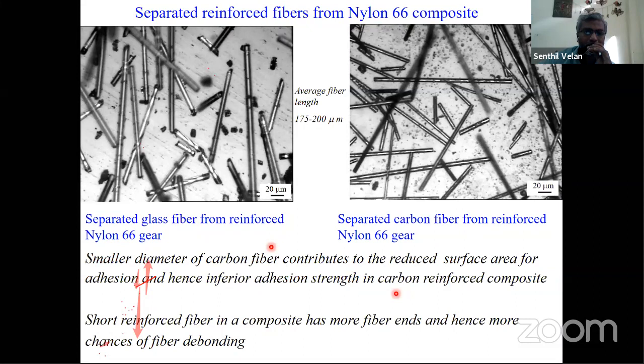What is more important is the size. The smaller diameter means, again, these are in microns. If you look into this, the average length is in the 175 to 200 micron range, and the diameter is in the range of 10 micron. So very small deviation, you don't find much difference between this and this. But that is why this is called critical fiber diameter, critical fiber length. These are very crucial. So though carbon is expected to be a superior material, because of this reduced surface area, your adhesion is seriously getting affected.